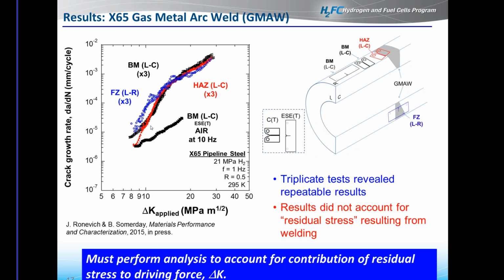So as you look at these curves, first of all, the base metal tested in air, as you see in the black here, this is the typical trend that you see in a more inert or air environment, where you see a very linear trend: with increasing delta K applied, you get an increasing crack growth rate, and that linear response is pretty common.